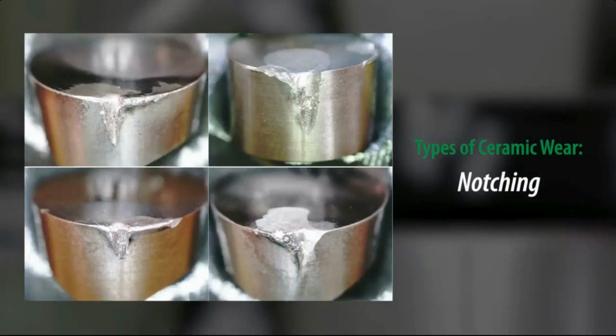Our next kind of wear is notching. This is a thermal mechanical type of wear. It's a special case of mechanical abrasion that occurs when the surface of the machined material exhibits heavy strain hardening, also known as work hardening, or when a hard scale is present on the outer surface. Since the hardness of the surface layer is higher than the hardness of the material deeper in the cut, this can lead to higher heat generated in the portion of the cutting zone at the surface.